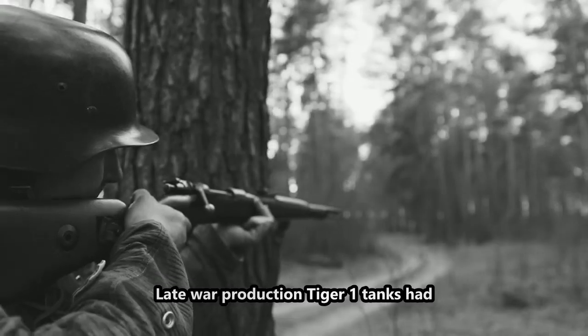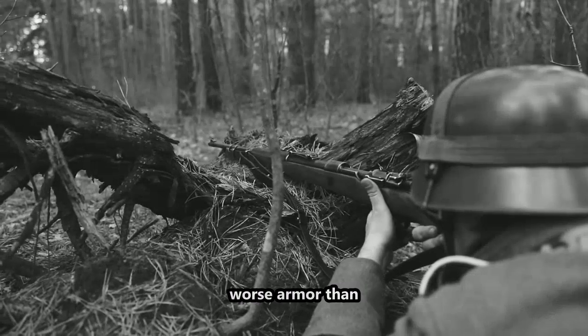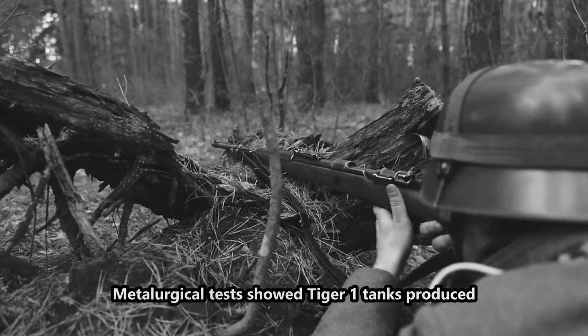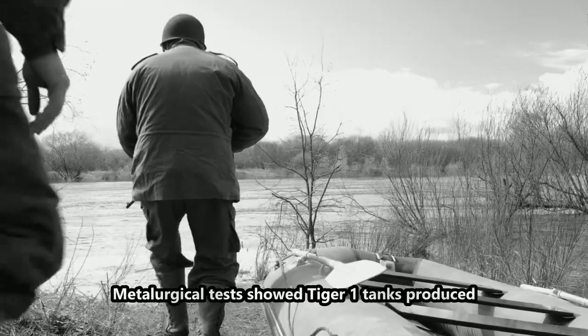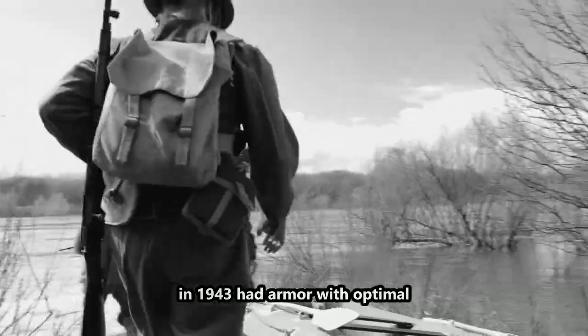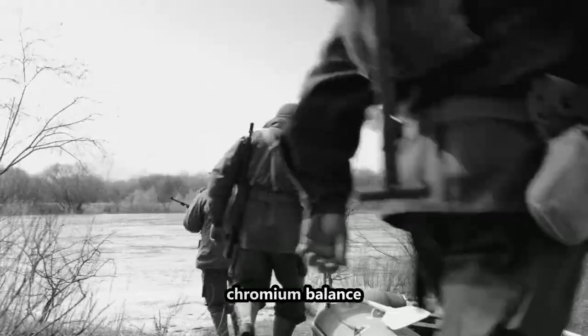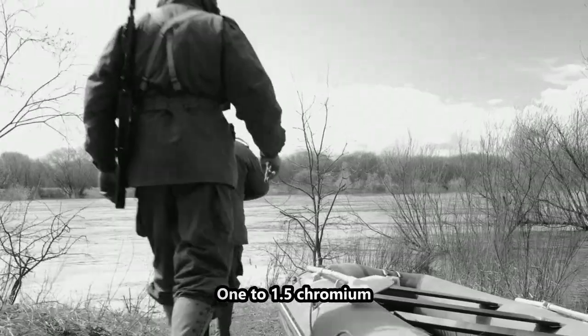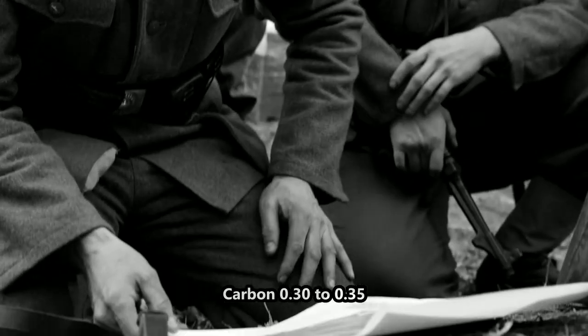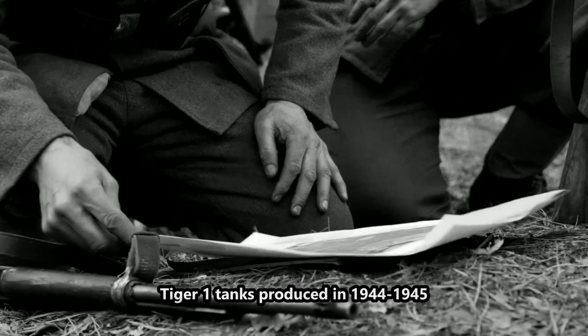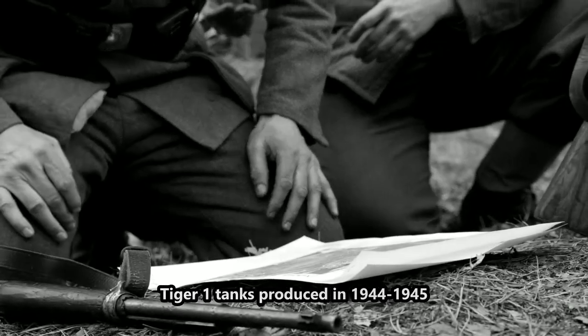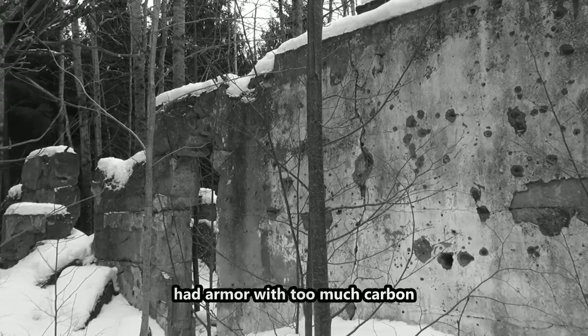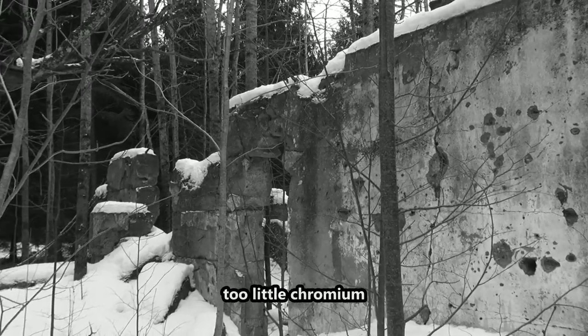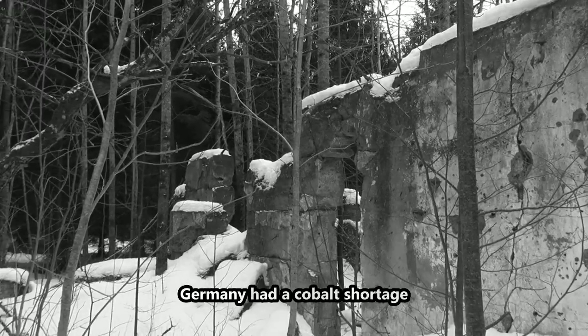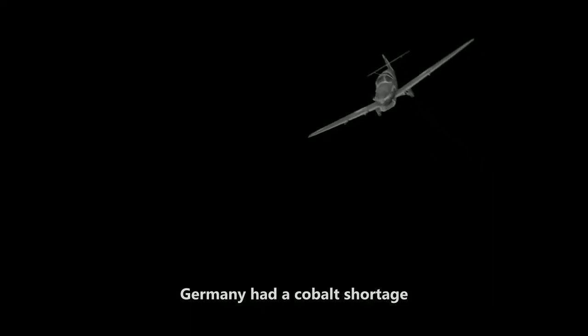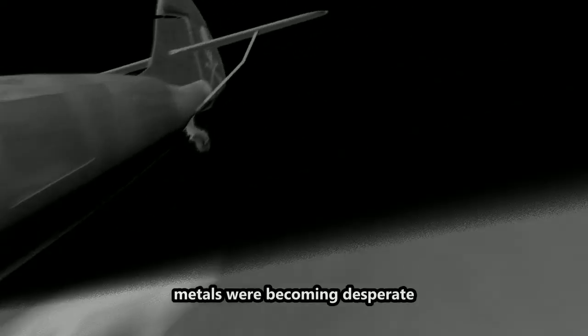Late war production Tiger I tanks had worse armor than earlier models. Metallurgical tests showed Tiger I tanks produced in 1943 had armor with optimal chromium balance, 1 to 1.5% chromium, carbon 0.30 to 0.35%. Tiger I tanks produced in 1944-1945 had armor with too much carbon, too little chromium. Why? Germany had a cobalt shortage. Alloying metals were becoming desperate.